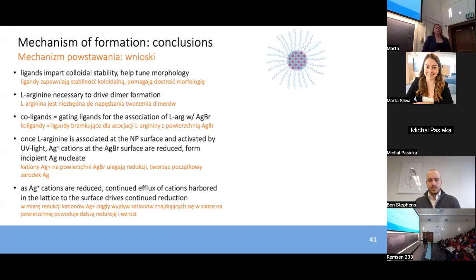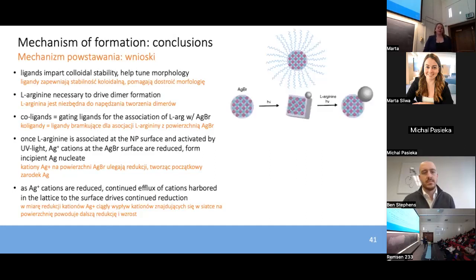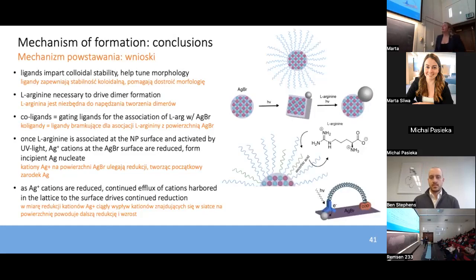So just to recap all that I've told you about the mechanisms of the silver bromide and silver-silver bromide dimer formations, we have shown that the oleate ligands are necessary to stabilize the host nanoparticles and also drive the formation of those dimers. We know that L-arginine is necessary to drive the formation of that dimer product. Without L-arginine, all we see is a change to that cubic morphology of the silver bromide host. Only when we introduce L-arginine do we get the propagation of that initial silver nucleate and the formation of that silver-silver bromide dimer.